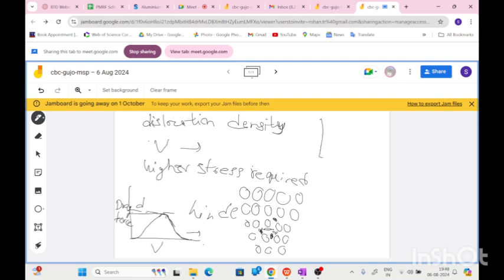Another effect on the increase in velocity comes with temperature. It means if temperature is increased, for a defined width, if we plot drag force versus velocity, this is for T1, and for higher temperature this will shift to higher velocity. So T2 is greater than T1, and for higher temperature the velocity of the dislocation is higher, V2 and V1. That's why we see that with an increase in temperature the plastic deformation is easier, because less drag force is required to move the dislocation through the impurity atoms.